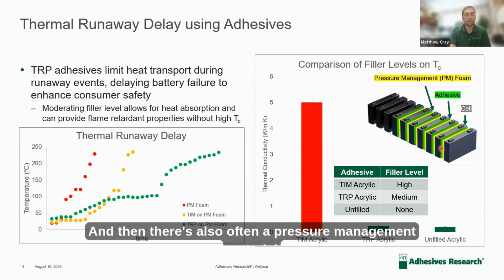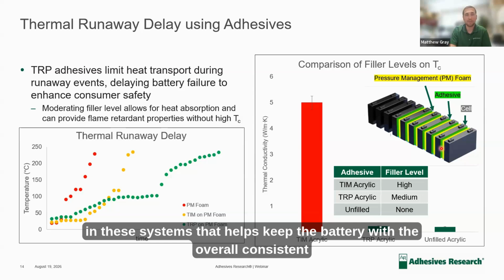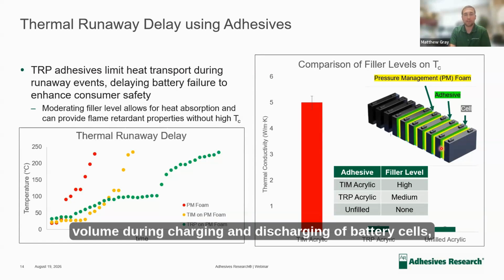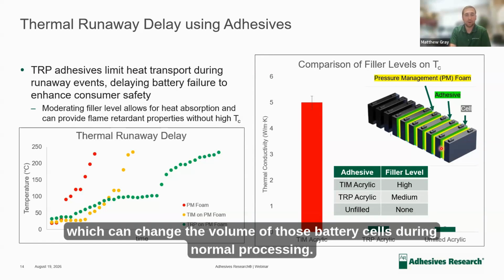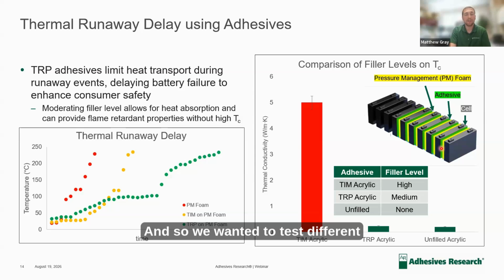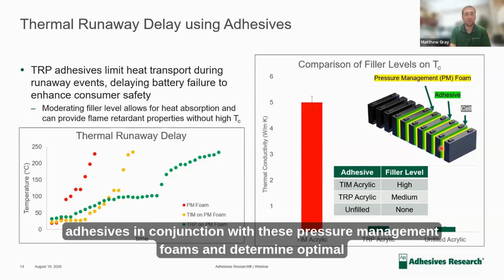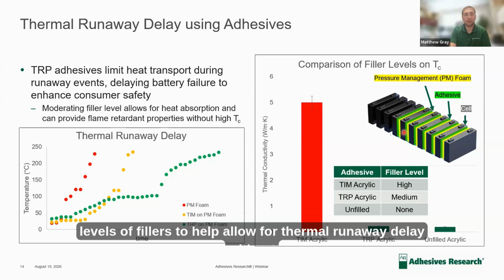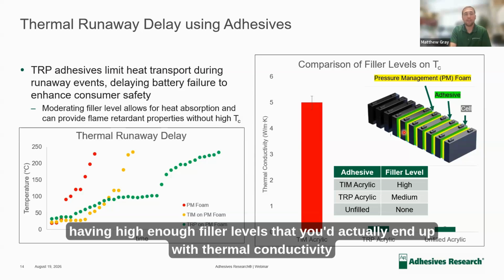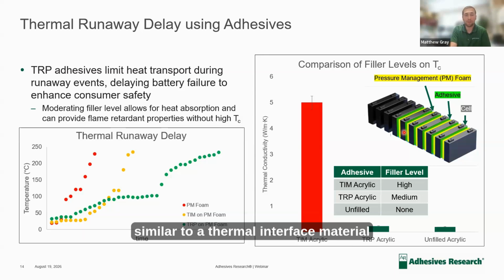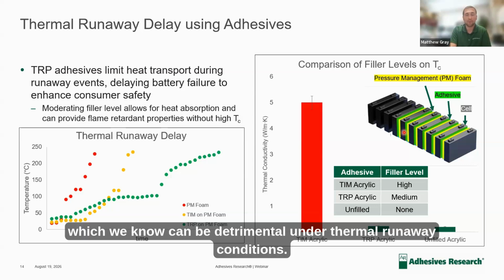Then there's also often a pressure management material in these systems that helps keep the battery with the overall consistent volume during charging and discharging of battery cells, which can change the volume of those battery cells during normal processing. And so we wanted to test different adhesives in conjunction with these pressure management foams and determine optimal levels of fillers to help allow for thermal runaway delay without having high enough filler levels that you'd actually end up with thermal conductivity similar to a thermal interface material, which we know can be detrimental under thermal runaway conditions.